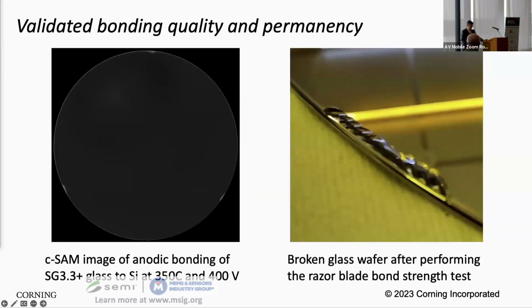And the quality of the bond is indicated on the left side. This is the acoustic image of a bonded wafer, and there's really no evidence of any voids or bubbles in the bonded wafer. And then the permanency of this bonding, typically we do a knife edge insertion from the seam. And if glass breaks, we know there's enough strength to indicate it's a permanent bond.